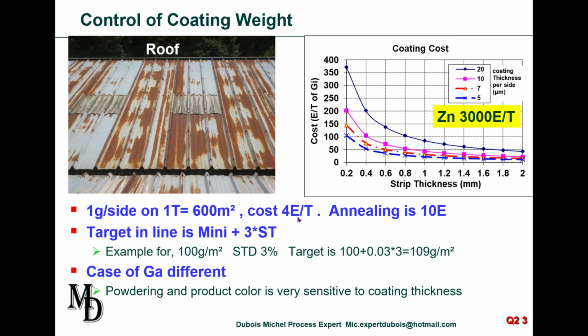Is that high or not? Just as a comparison, annealing costs about 10 euro, not more than that. So you see that improving the heat yield on a furnace is not easy, but saving 1 gram becomes really interesting. And also the fact that the final customer requires a minimum coating weight.